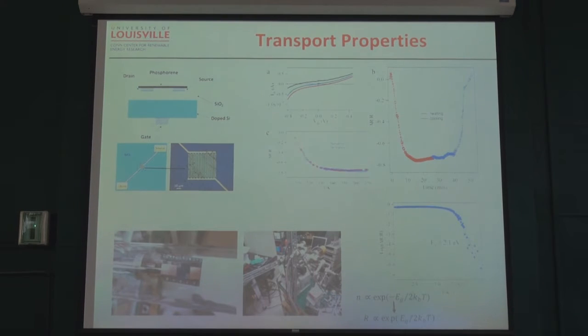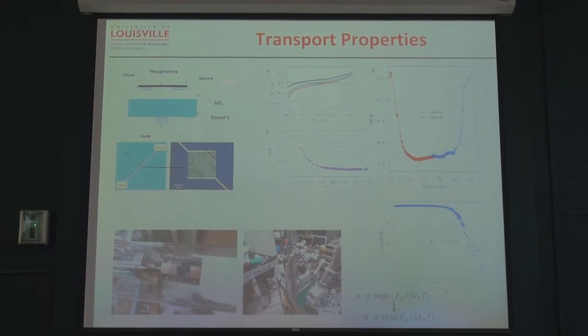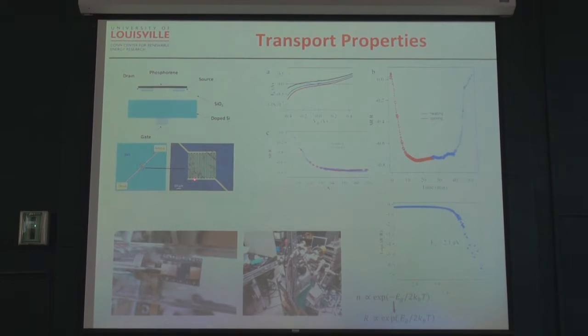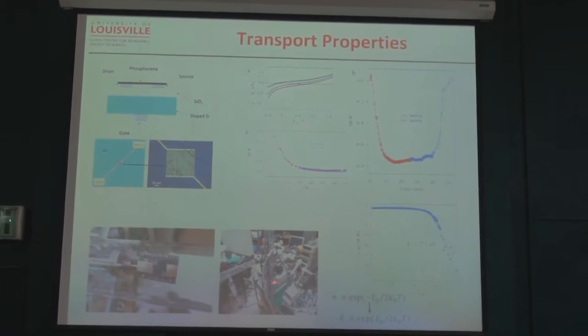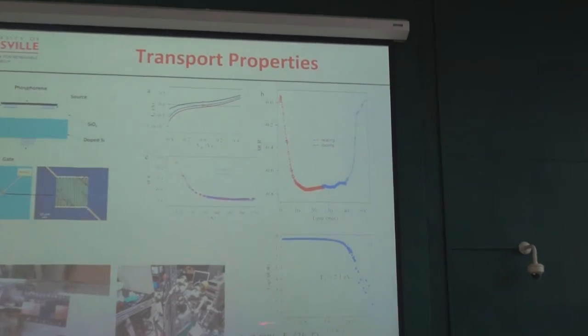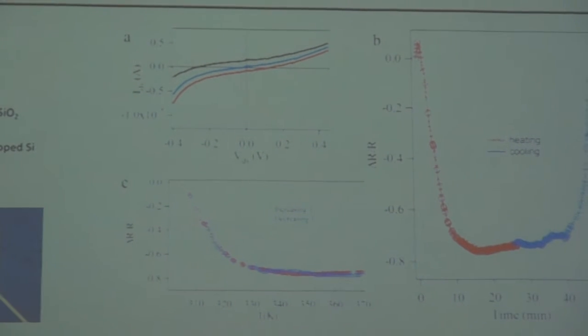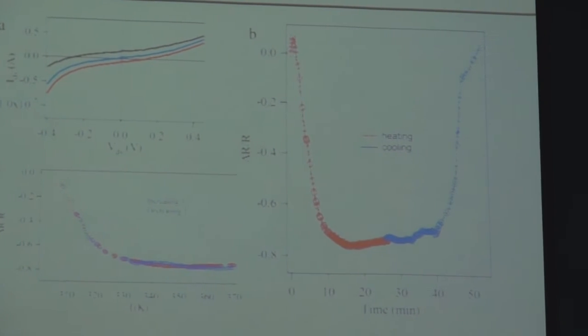Okay, so these are some of the electronic properties we have. Usually we use the interdigitated pattern. Then we have phosphorene. We look at the resistance and resistance change and IV characteristics. This is how an example is connected. If you look at the temperature dependence, you can get your band gap. That also comes very close to 2.2 electron volts.